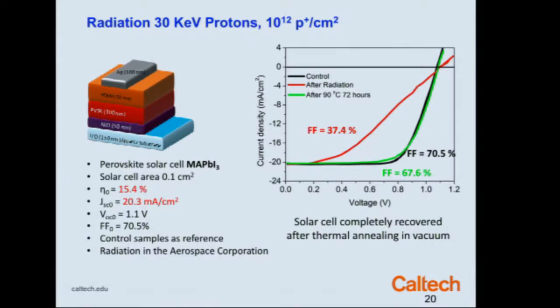Here is with proton irradiation. And this story's plot thickens a little bit. Same kind of cell here. It's an absorber layer. We have electron and hole transport layers here, nickel oxide for hole and PCBM for electrons, and then we have a transparent substrate here that this has been made on. So upon proton irradiation, we find that the solar cell voltage stays exactly the same. The short circuit current density stays exactly the same, but the fill factor changes. That seemingly suggests that there's some series resistance in the cell, in this absorber layer. We think it might be due to proton-induced deactivation of doping, or it may be that it is changing the properties of the interfaces here.